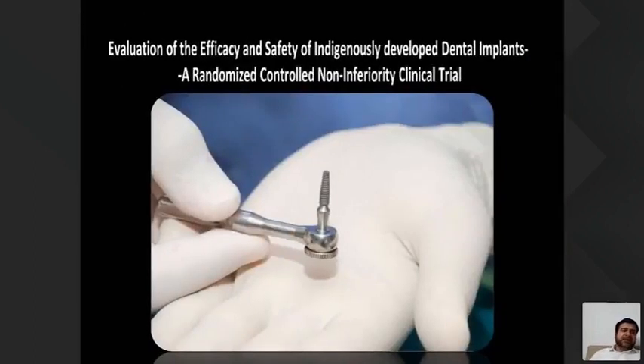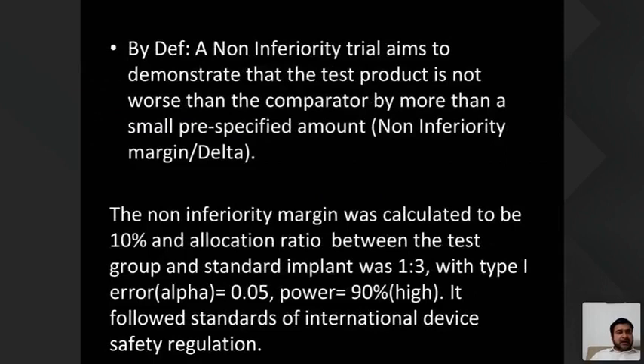Then we went ahead with the randomized controlled non-inferiority clinical trial. It was to evaluate the efficacy and safety of indigenously developed dental implants. Of course, the sample size was much larger than the phase 1 or first-in-man trial. So by definition, a non-inferiority trial aims to demonstrate that the test product is not worse than the comparator by more than a small pre-specified margin, or the non-inferiority margin, or delta. So the non-inferiority margin was calculated to be 10%. The allocation ratio between the test group and the standard implant was 1:3 with type 1 error. Now the power was high for the study, 90%, and it followed the standards of international device safety regulation, the Helsinki Agreement, the draft guidance document of CDSCO, of DCGI, and Class 2 Special FDA Consideration Act, and so on and so forth.